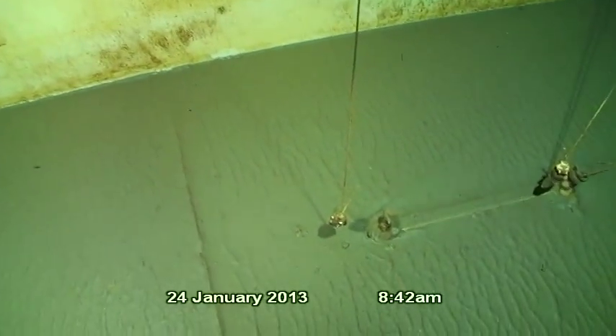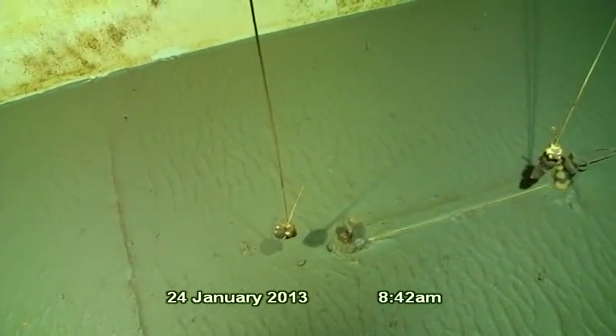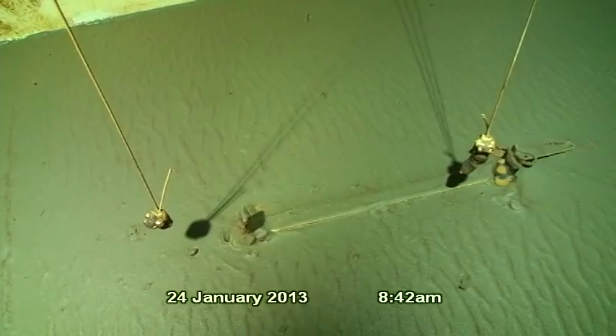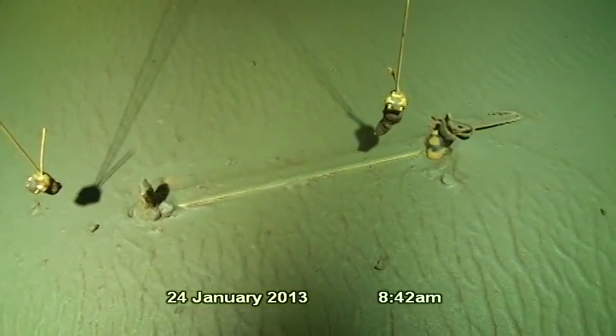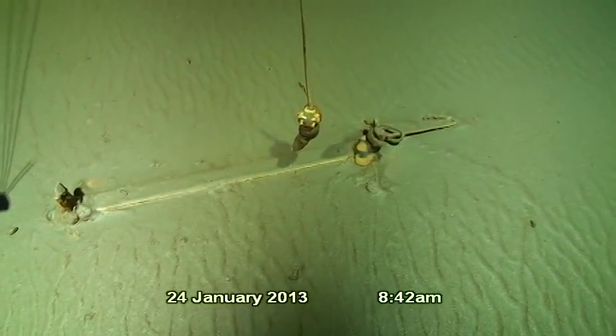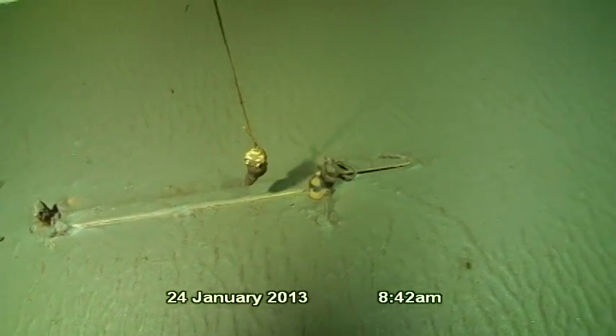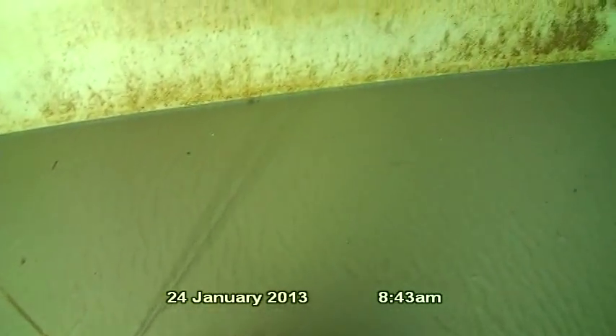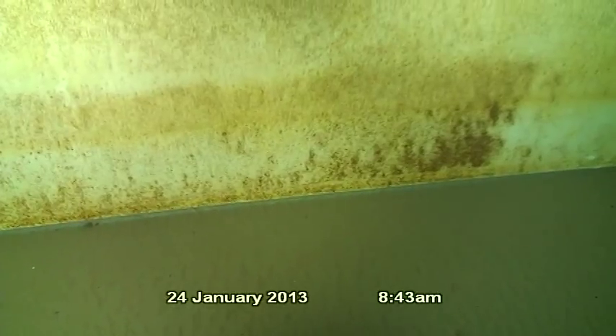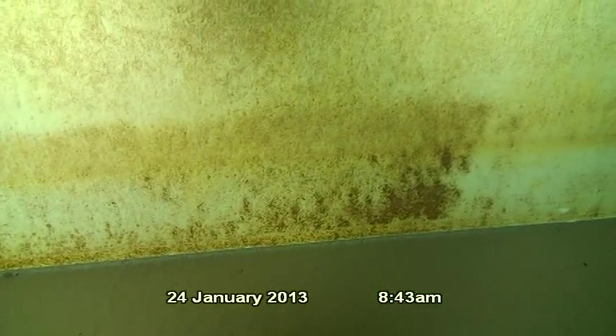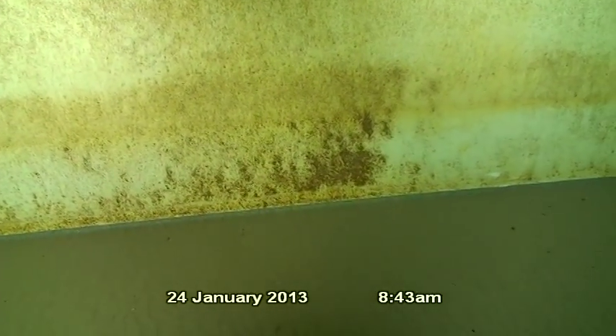Cracked delaminating epoxy coating has resulted in light surface corrosion in many areas on the shell near the manway and the target base. Corrosion has consumed portions of the target base. The guide wires for the target are no longer secured to the base. Dense corrosion is present on the target base in these areas. Additional corrosion is present here at the transition from vertical wall to floor next to the interior access ladder.